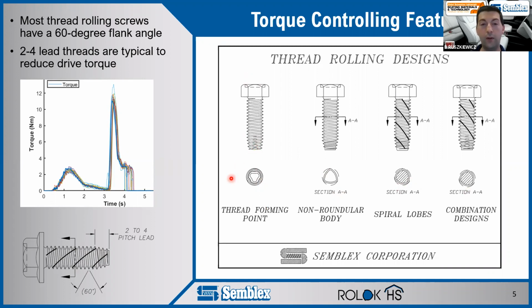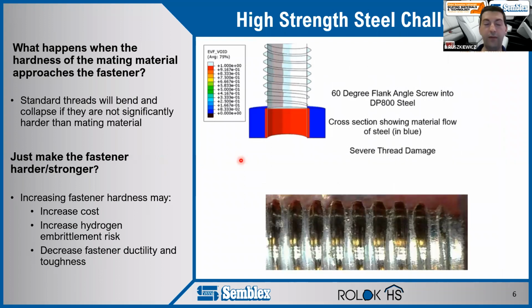Now, most traditional thread rolling fasteners have a 60-degree flank angle, and it's very important for what we're going to do with Rolok HS. The 60-degree flank angle is simply the angle between the thread faces. It's the same as a standard machine screw, which is where these thread rolling screws came from. However, as we saw in that video at the beginning, some of these fasteners just don't work when that steel starts to get hardened, whether that be from manufacturing operations or just from the steel being high strength on its own. So to look into this further, we looked at simulating a screw that was only a little bit stronger than the material it went into to see if we could duplicate what we saw in that video at the beginning.